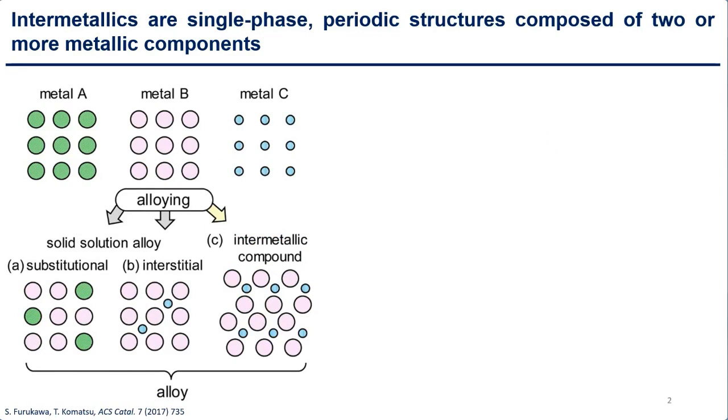Now, in catalysis, we are very familiar with utilizing alloys to control or understand how catalyst structure influences activity and selectivity. In most of these cases, though, we're using solid solution or random alloys. And in that case, it's difficult to define the exact location within the lattice that the second element occupies, relative to an intermetallic where the location of that additional element is well defined.